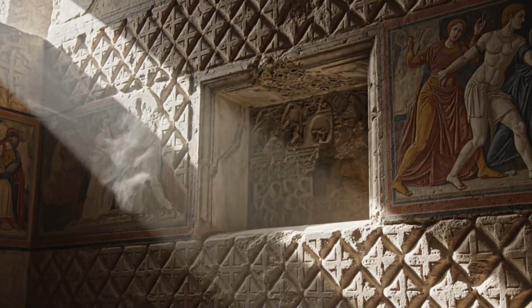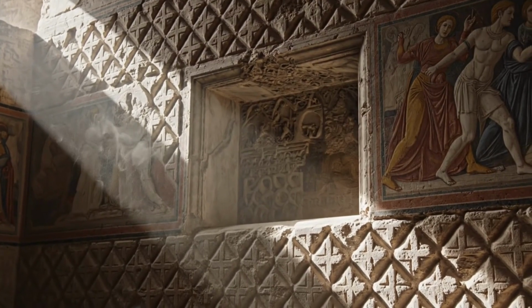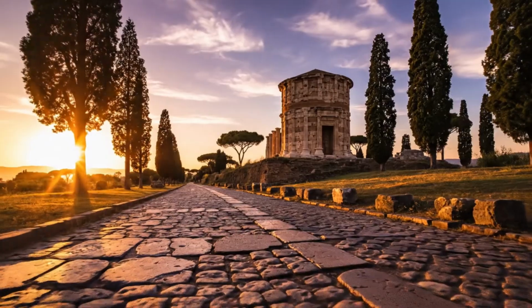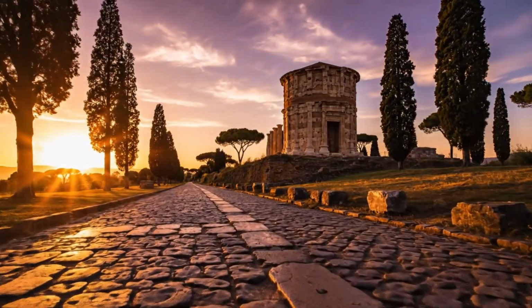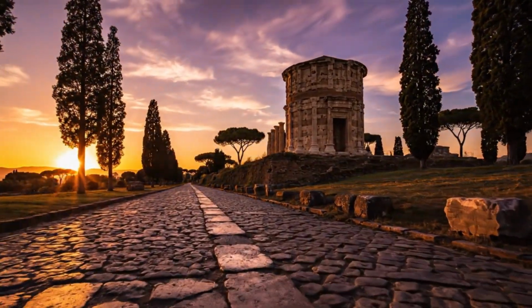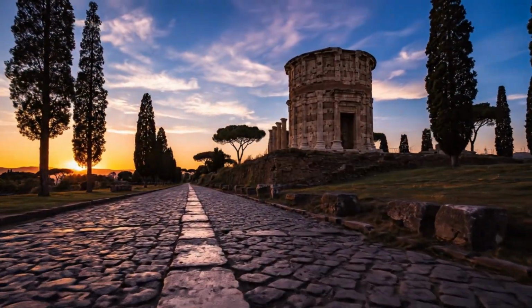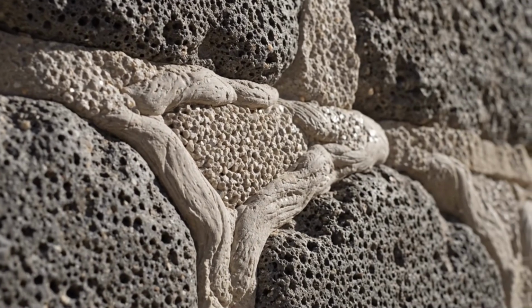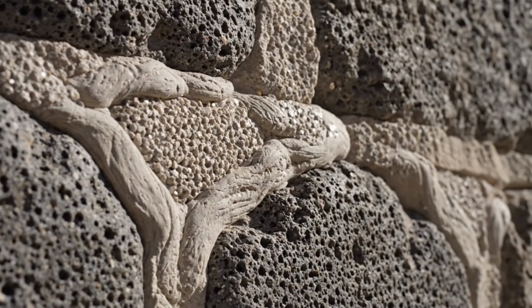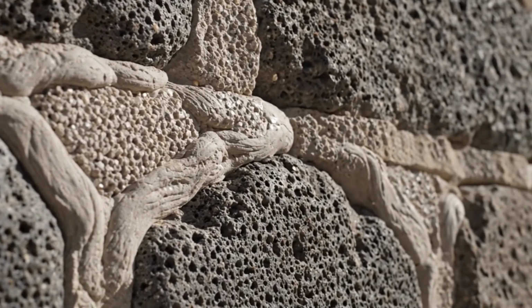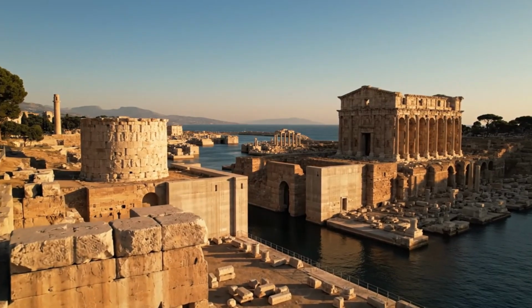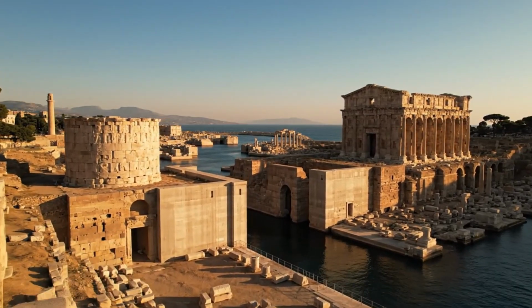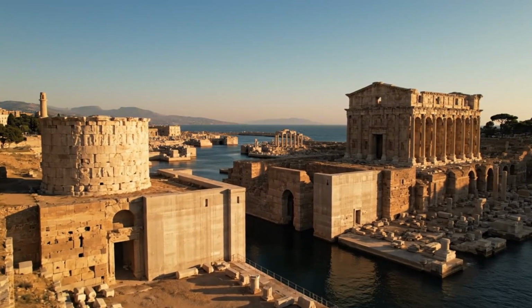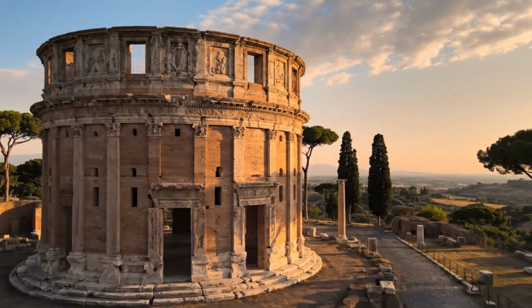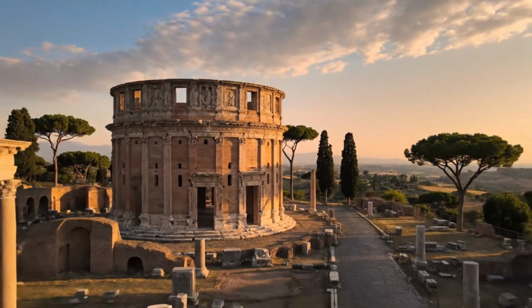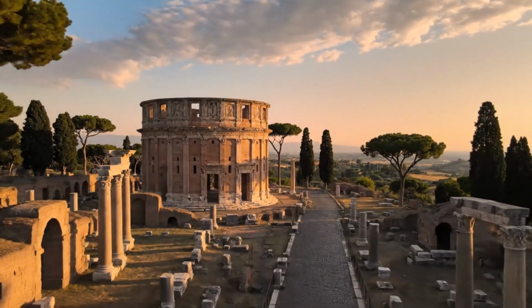Within that matrix, volcanic aggregates containing potassium-rich leucite gradually interacted with infiltrating rainwater and groundwater. Over centuries, the slow dissolution of leucite released potassium that contributed to the remodeling of the binding structure at the microscopic level. At the same time, the deliberate use of quicklime through hot mixing introduced lime clasts that acted as reactive reservoirs. When cracks formed, these inclusions enabled the precipitation of calcium carbonate, sealing fissures and restoring continuity.